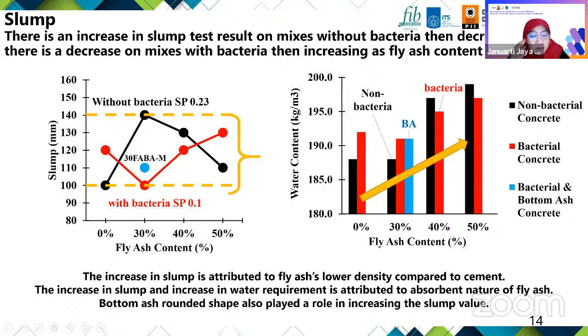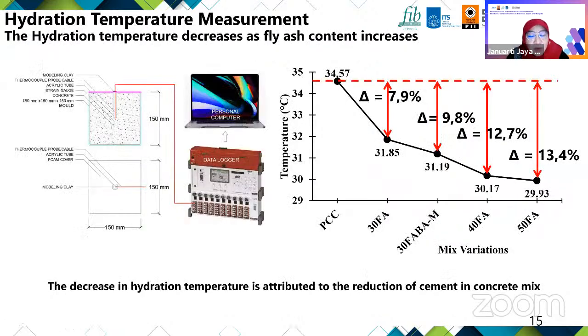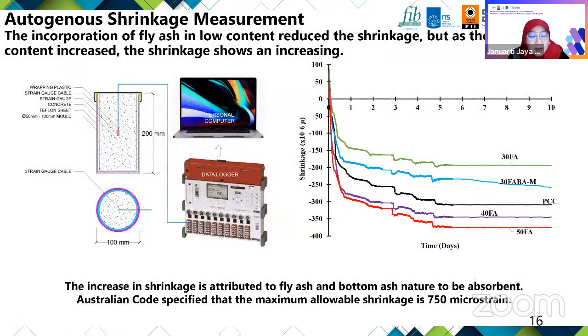And this is the result of temperature monitoring during the 24-hour hydration. The ash helps a lot to decrease the temperature by up to 13%. And something very interesting to see, I use my last experiment in Japan at the University of Tokyo to measure the concrete shrinkage for 10 days. I put an embedded strain gauge in the center of the concrete, and we can monitor the shrinkage during the hydration of the concrete up to 10 days.